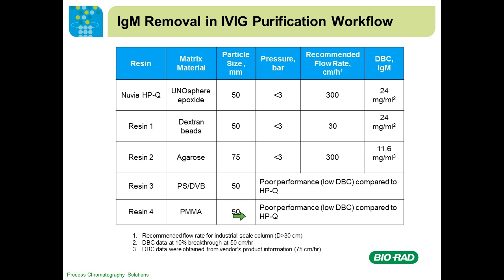Polymethacrylate beads are also a chromatography resin in the market, which often also have large pores, but the surface area is limited. Therefore, even though the pore size is big, the porosity combined with the smaller surface area causes the binding capacity to drop.